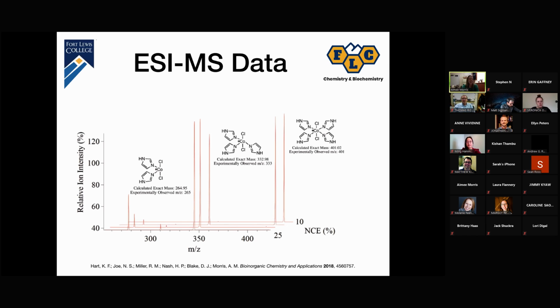And so he was able to take our compound. And when we look at the electrospray mass spec, we can not only see the parent cationic coordination complex, but we could also increase the normalized collision energy. And as you increase the normalized collision energy, we also saw more of the fragments populating. And so this was really strong evidence for us, again, based on the structure of what was happening there.